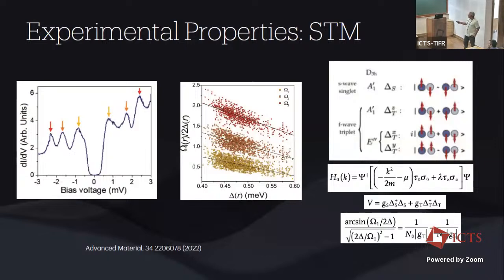So they claim that they can explain this idea by considering that, remember, this is a broken inversion superconductor. So this can naturally mix your even and odd parity superconducting states. So they said that there is a mixing of an F-wave triplet to the S-wave singlet state out here, which can lead to, using an equation of motion method, the formation of a Leggett mode along these lines. So this paper, in that sense, was a first proposal that there is some unconventional pairing mechanism happening in the system which we need to understand better in the monolayer system.